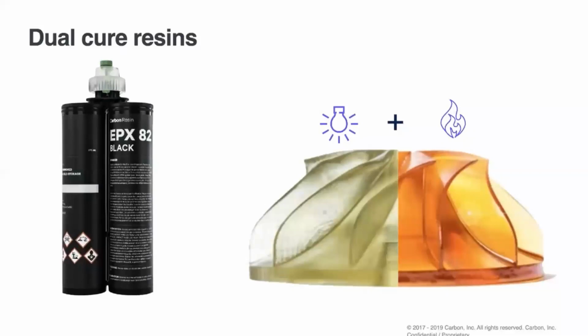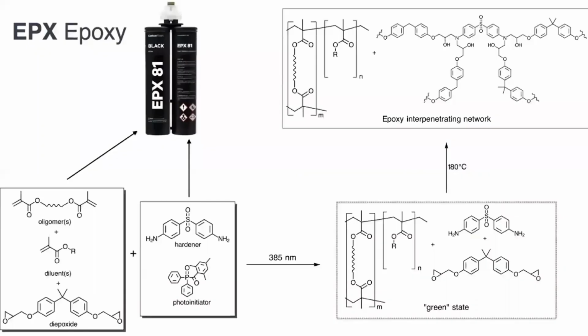So our approach for doing this, Jason and the team and Matt and others in our team and Marie really developed a process we call dual cure resin. So we basically combine reactive liquids, and think about your favorite epoxy where you have a diepoxide and a diamine coming together, but we also combine that with UV curable chemistry. Reactive liquids themselves are typically not UV cured, they're just reactive, give great materials. Most people in 3D printing never went down the reactive liquid approach because their printers were too slow. Because we're printing really fast, we thought we can get into this chemistry, but we also needed to make them reactive with light. We call that dual cure.